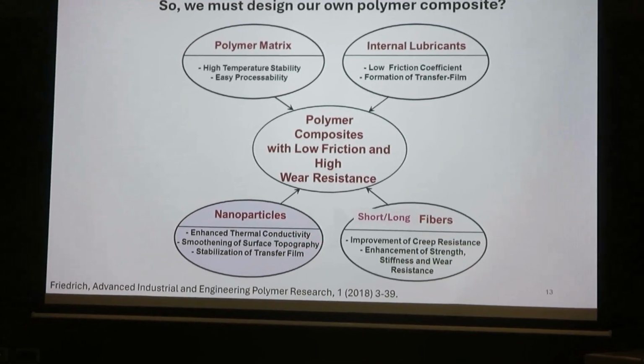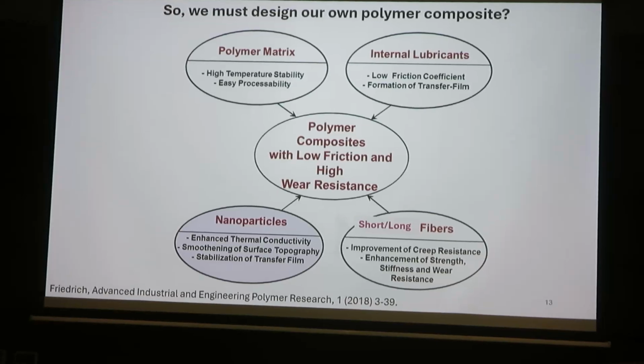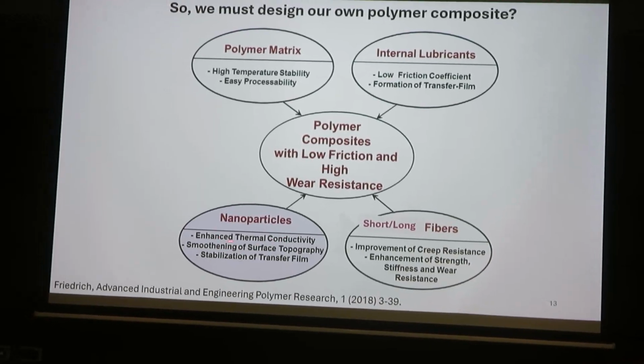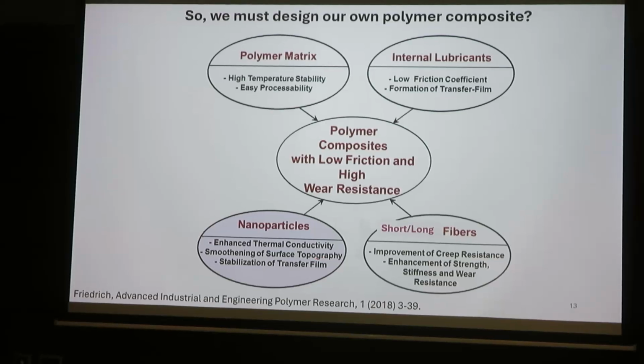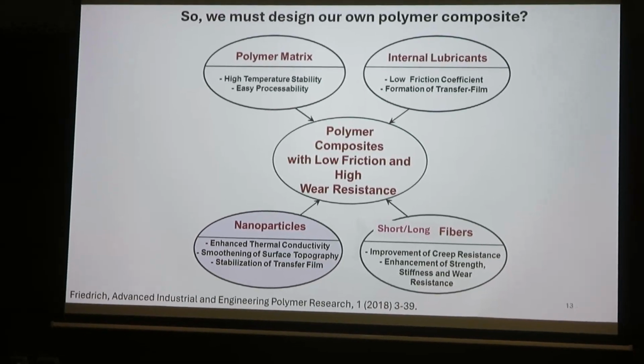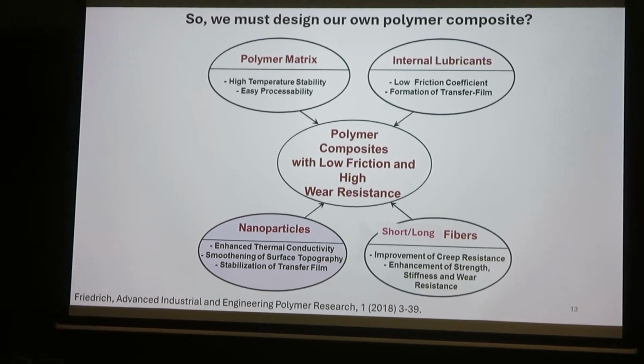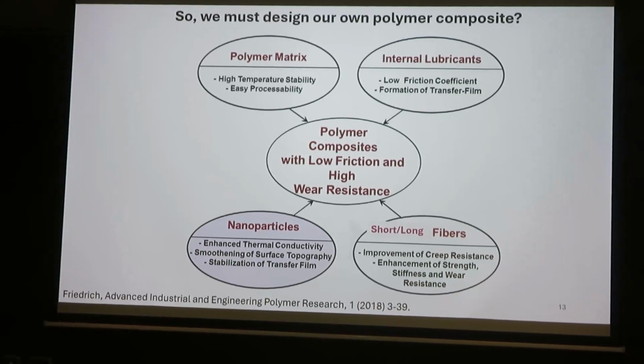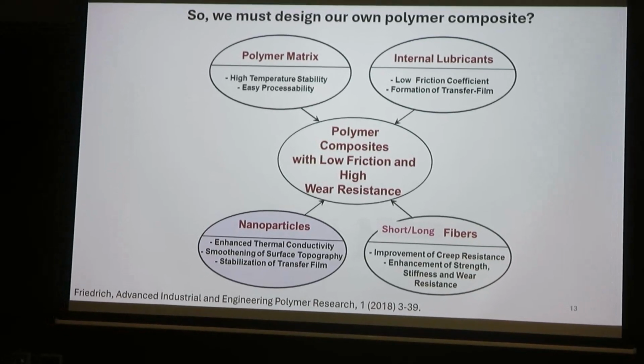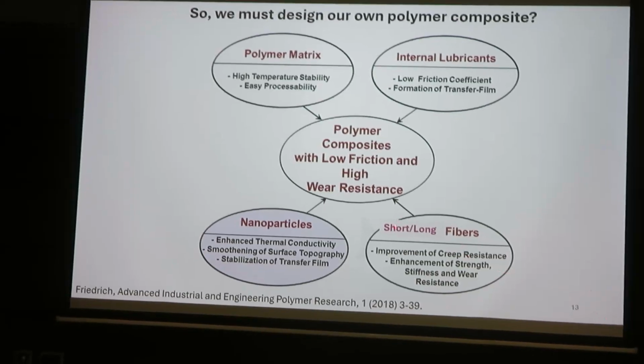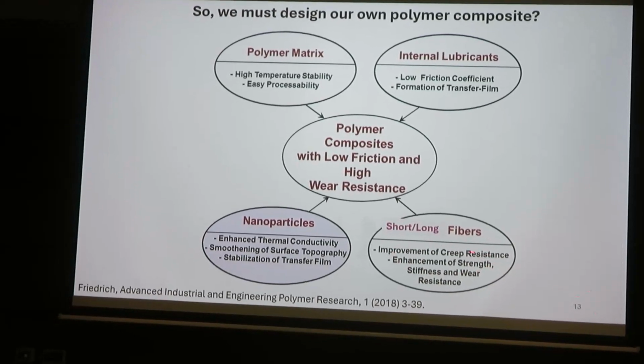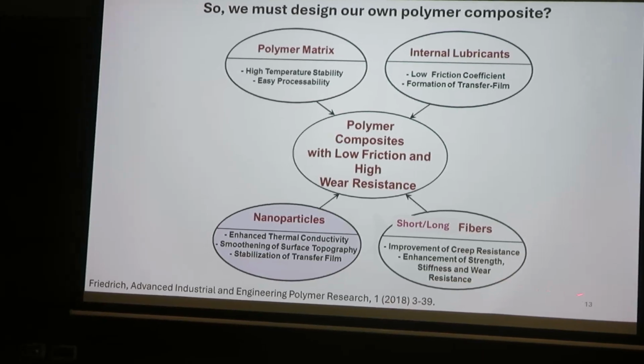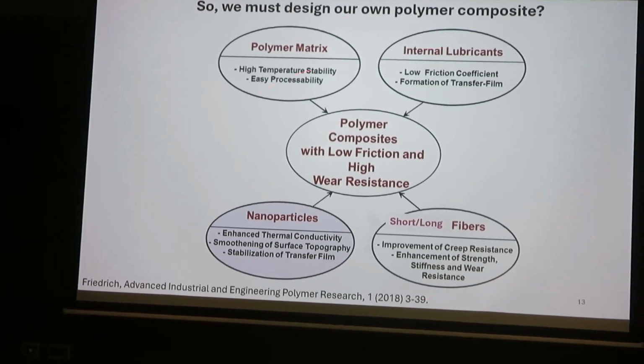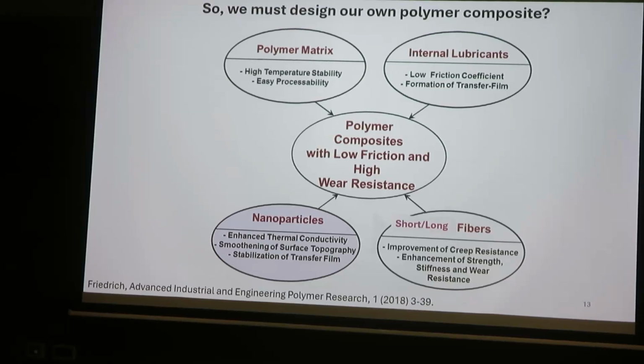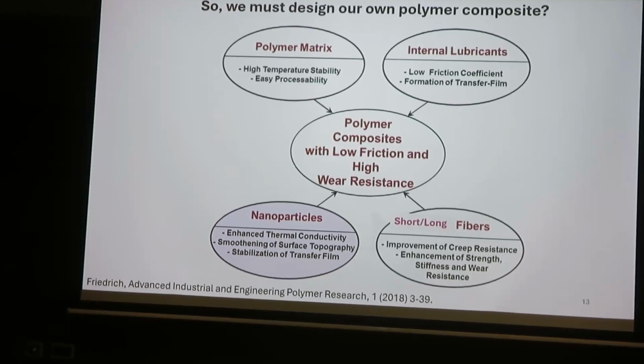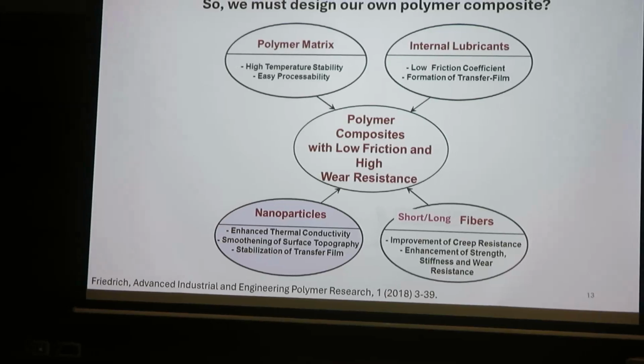For example, multi-wall CNT can enhance the thermal conductivity. Smoothing of the surface topography. Many times you will see that what the nanoparticles are doing is actually polishing the counter surface, and that's why the wear will go down. And short or long fibers will enhance the creep resistance, strength, stiffness. So this is the whole recipe of how we can make polymer composites for most of the engineering applications.